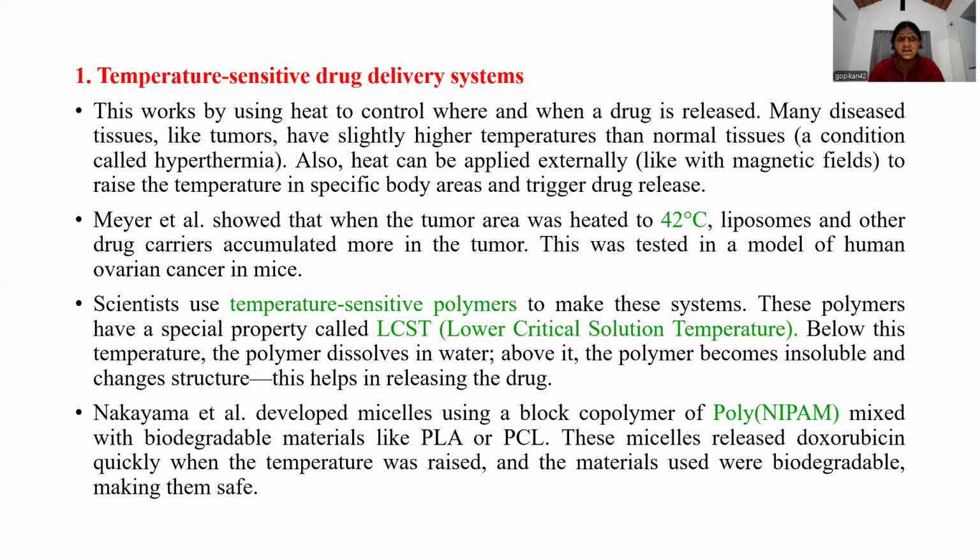Scientists also use temperature-sensitive polymers to make this system. These polymers have a special property called LCST, the lower critical solution temperature. Below this temperature, the polymer dissolves in water, and above it, the polymer becomes insoluble and changes structure. This helps in releasing the drug from the delivery system.